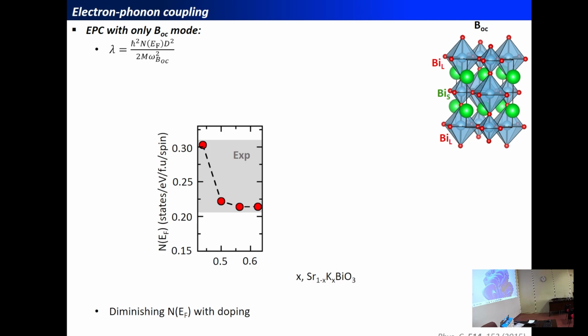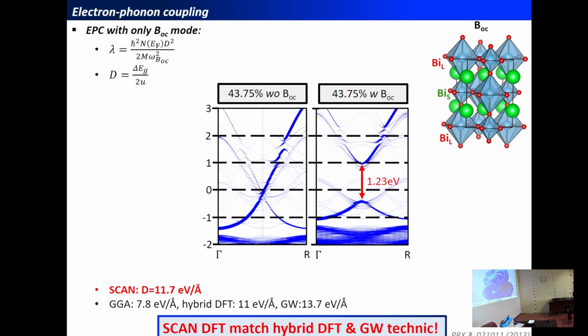So we need the three terms, the density of states at the Fermi level, the frequency of the mode, and also the reduced electron-phonon coupling element. Regarding the density of states, in the superconducting region, when we have the parabola, we observe a decreasing density of states oscillating between 0.3 and 0.2 states per eV per formula unit per spin channel. And this value is compatible with the experimental reports around 0.25 plus or minus 0.05 for these systems. And so we have a diminishing density of states at the Fermi level when we put more and more potassium in the material. So the next quantity we need to compute is the reduced electron-phonon coupling matrix element.